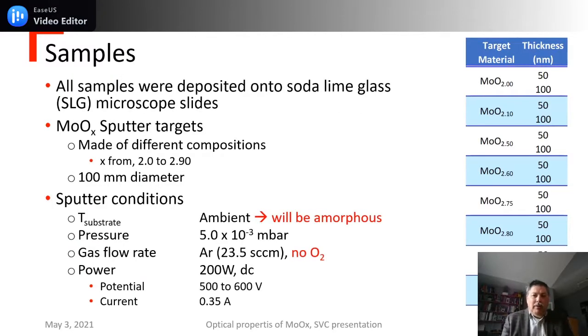We made a number of samples over a range of target compositions from having stoichiometry of 2.0 all the way to 2.9, and in two different thicknesses, nominally 50 nanometers and 100 nanometers. Today I will discuss only the 50 nanometer films. The 100 nanometer films are for the most part very similar, but subtle differences exist. Don't have too much time today to describe that work.